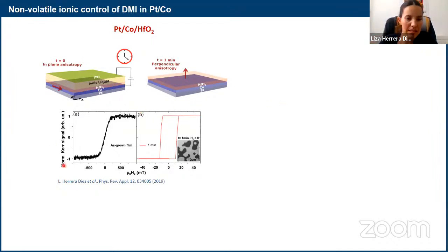So here what you see on the left is the loop that we get out of plane for the as-grown system, which does not show perpendicular anisotropy. While after 1 minute of gating, we can see that it nicely goes to a perpendicular state with very nice domains.